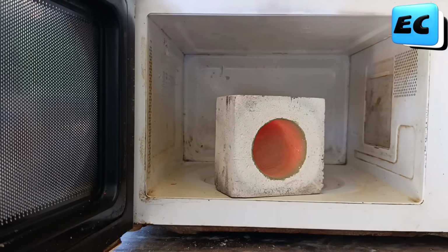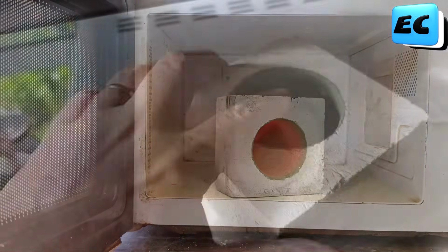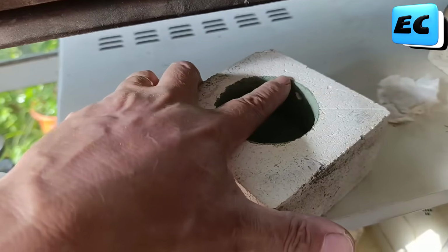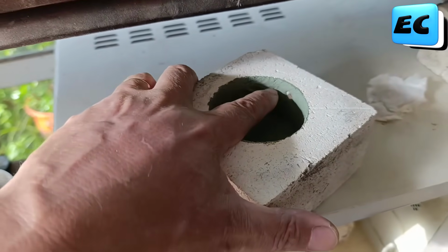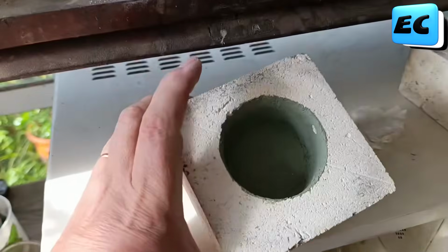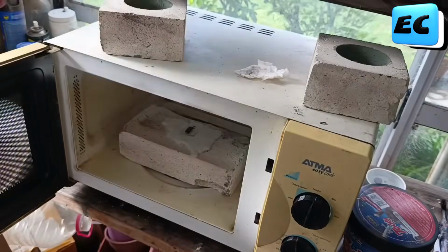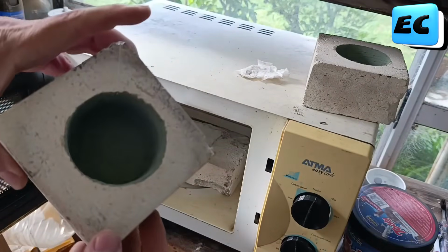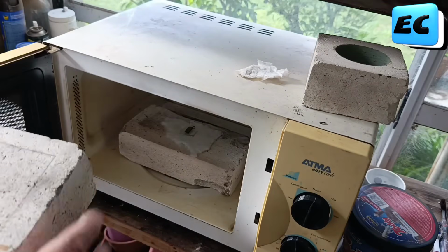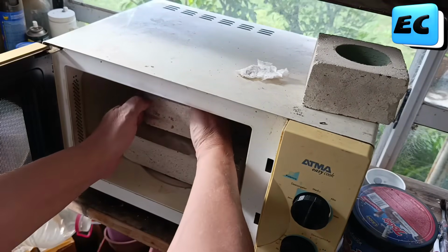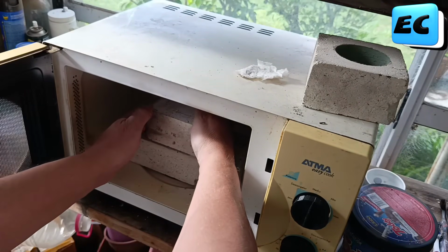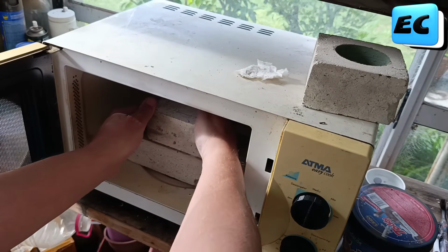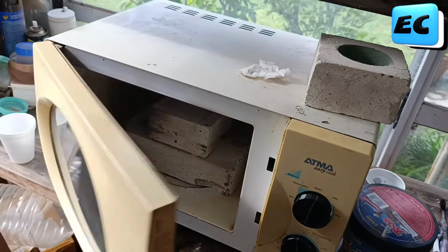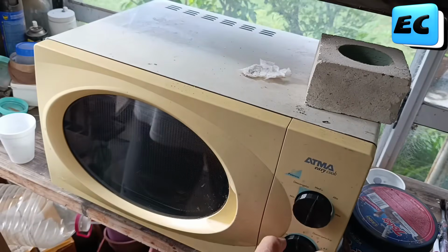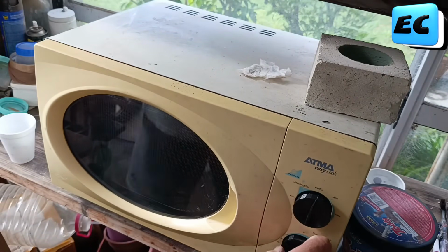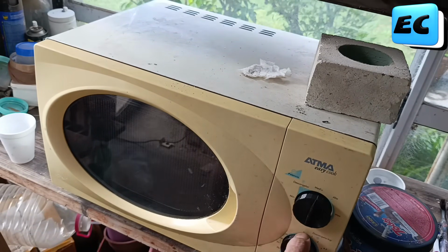You'll see that the silicon carbide walls, which were soft and crumbled easily, have vitrified and now have a hard, stone-like consistency. It's very, very firm. That's sometimes due to the big thermal difference between the carborundum and the alumina, because alumina doesn't heat up in the microwave. Sometimes the brick can crack, and sometimes even the carborundum itself cracks too, but it still works, so don't worry if there's a little crack.